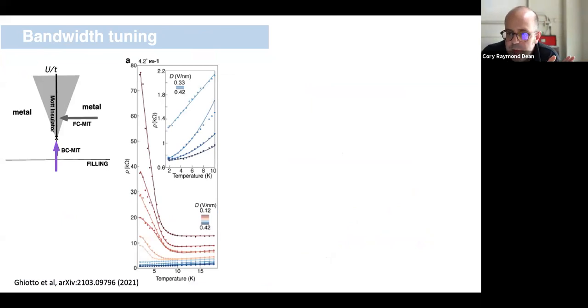So we dope in and out of the half band filling regime. What happens if we bandwidth tune? Here I'm sitting at fixed half filling and we apply a displacement field. So this curve is a large displacement field and this is a small displacement field. And what we see is that here we can tune from an insulating state to a metallic state by bandwidth tuning alone. Again, sitting at fixed filling.